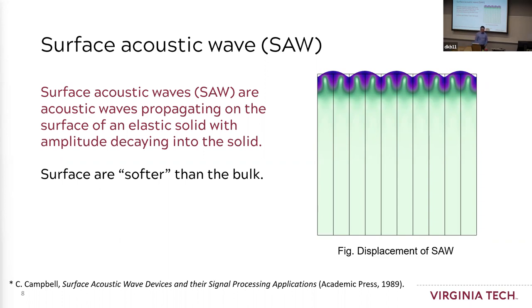So people may ask why there are such kinds of waves. The short answer is you can imagine the surface, without the top bonding to other material, usually becomes softer. And when it's softer, it can support the mode. It's like isolated from the bulk modes. It usually features a lower phase velocity of the acoustics, and they do exist.